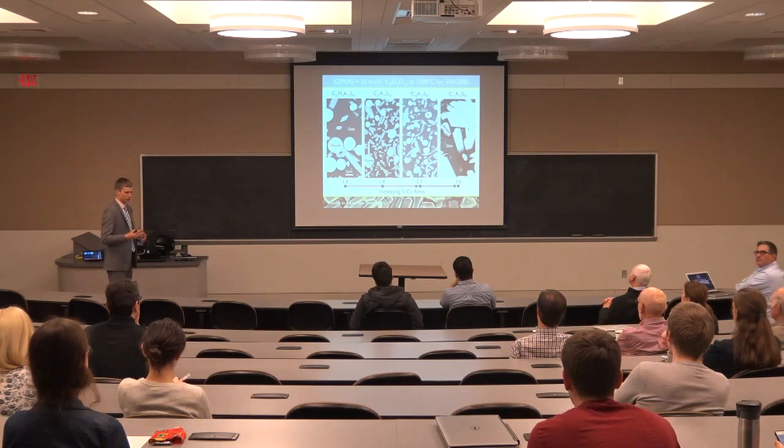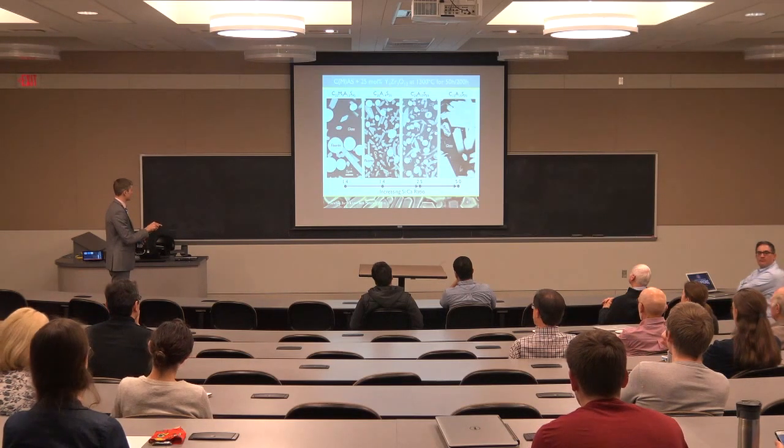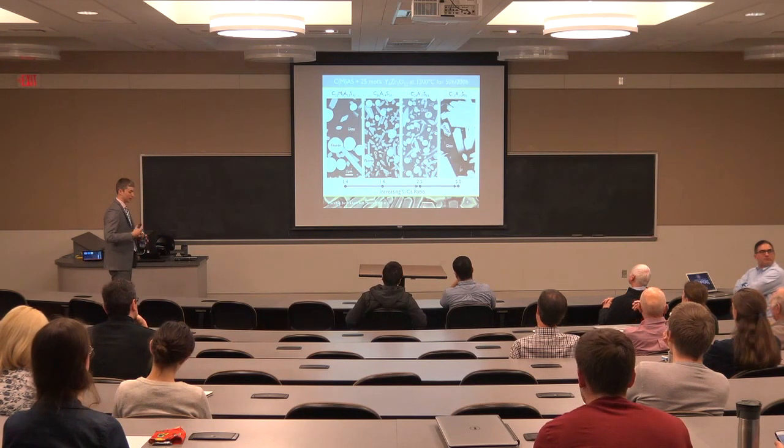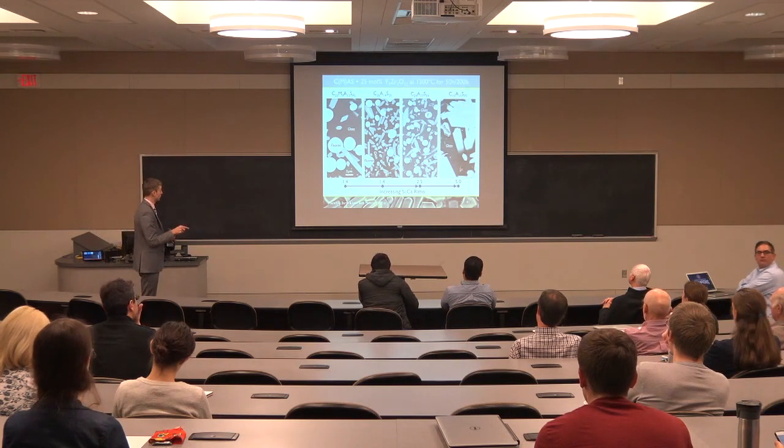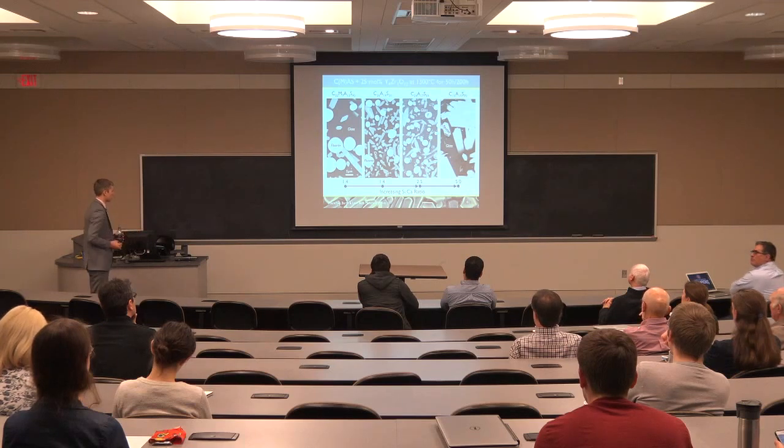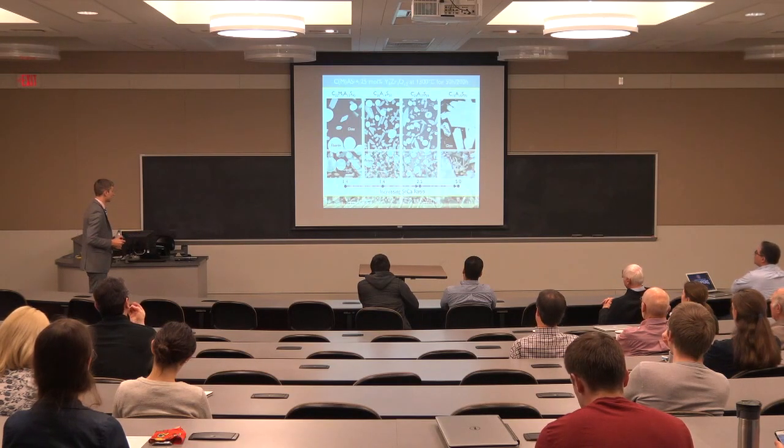has less yttria, but still some yttria in it. And the rest of the yttria goes to form apatite. So again, we get apatite in every case. In this scenario, the silica activity is actually high enough that we also precipitate out the zirconium silicate or zircon phase. So again, we're trying to understand the limits of the system.